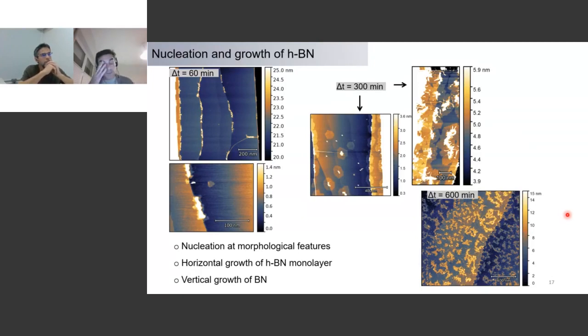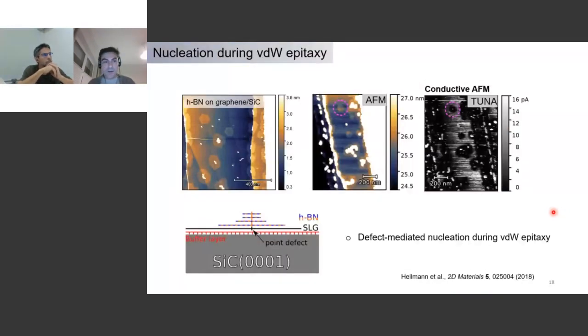I mean, when you grow in MBE, you would expect a nice layer-by-layer growth where your surface is perfectly smooth, atomically smooth afterwards. And this is not the case here. And we believe this has to do with the fact that this nucleation is so disordered and you have vertical growth competing with horizontal growth. And I want to dig a bit more into this nucleation here, because what we see, as I said, are these morphological features and the nucleation taking place there.